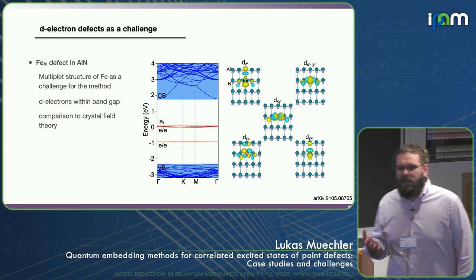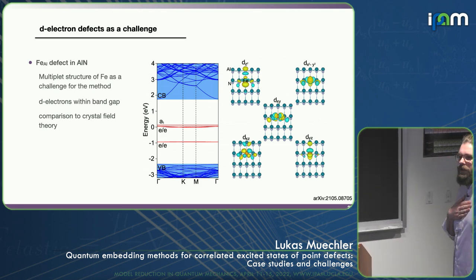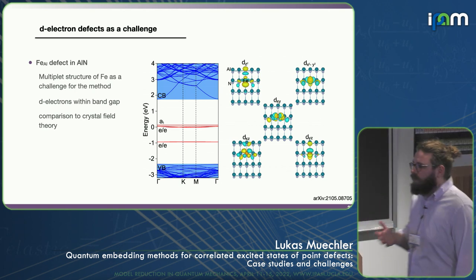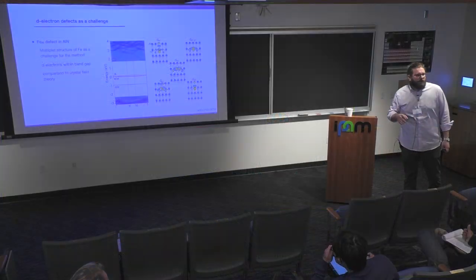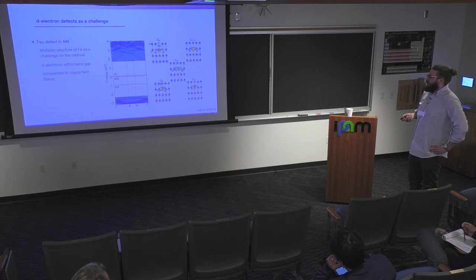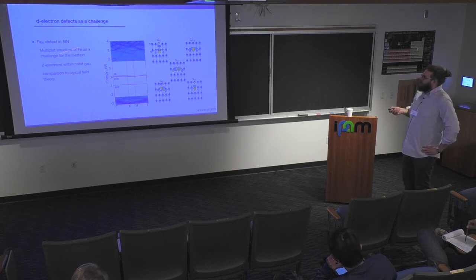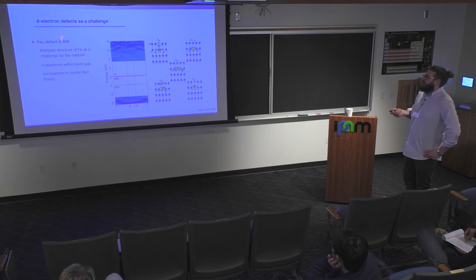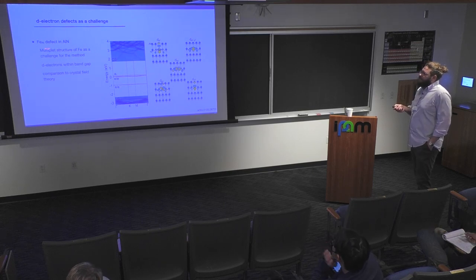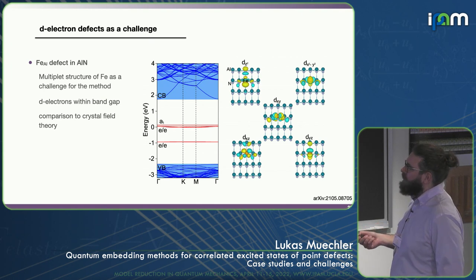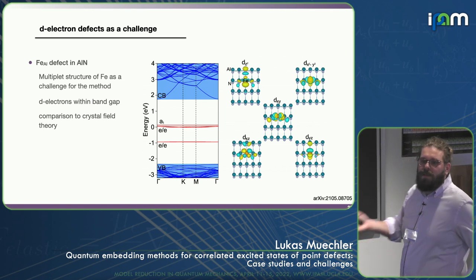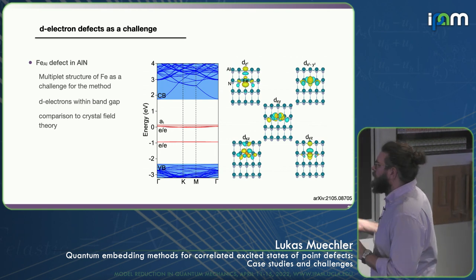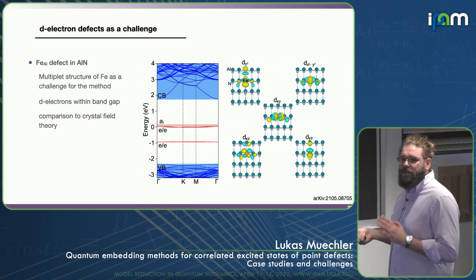What I take from this is that I'm already very happy if I get qualitatively right results. Quantitative accuracy requires a lot of work. We also thought: can we find something where this goes completely wrong? So we looked at a more challenging case. You substitute aluminum with iron in aluminum nitride — the d orbitals of iron sit in the band gap of AlN. This is a good test because in gallium nitride, some states would fall in the valence band, creating ambiguities. This is basically a general chemistry question: you have an iron atom in a C3V crystal field — what are the level splittings? The symmetry goes from Td to C3V, giving two doubly degenerate states and a singly degenerate state.